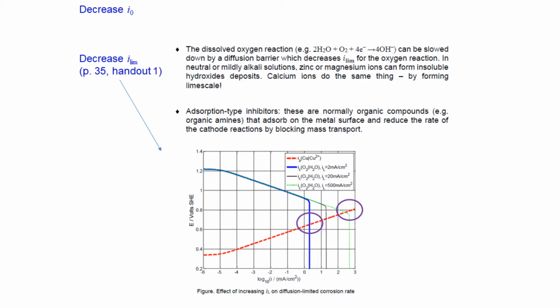So if instead we have dissolved oxygen and want to slow the rate of corrosion it causes, the best way is to slow down the diffusion limited rate at which oxygen is supplied to the metal surface. You can do that by removing oxygen from solution so it's low concentration, hence low diffusion limited supply rate. One of the more interesting ways to cut down the diffusion limited rate of oxygen supply is to operate in a system which fills up with lime scale.